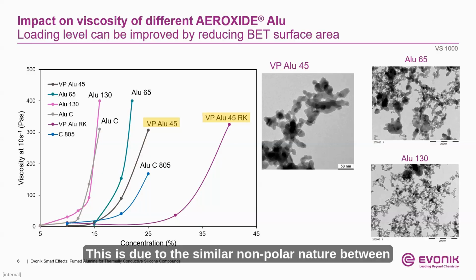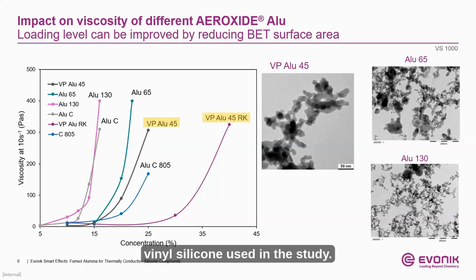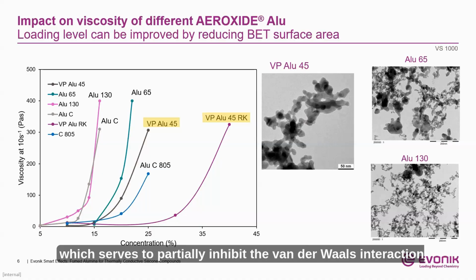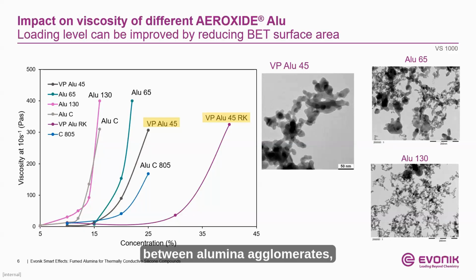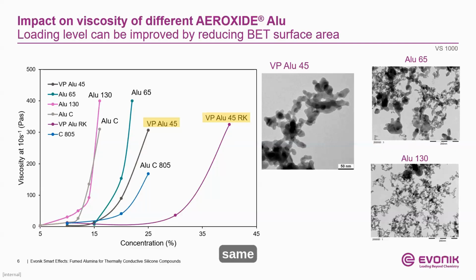This is due to the similar nonpolar nature between the hydrophobic treatment of the RK product and the vinyl silicone used in the study. The similar polarities between these two materials allows for greater resin interaction with the fumed alumina, which serves to partially inhibit the van der Waals interactions between alumina agglomerates that help generate viscosity in the system, allowing for higher loading levels of the material with less upwards viscosity impact.